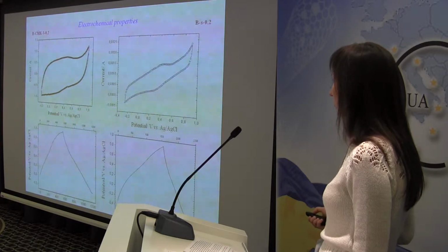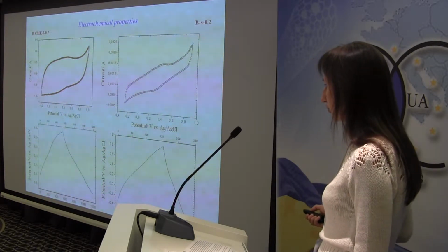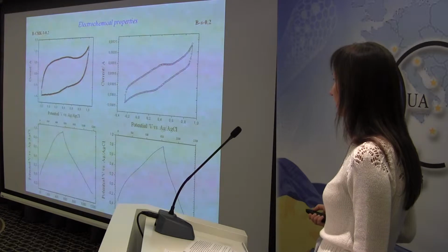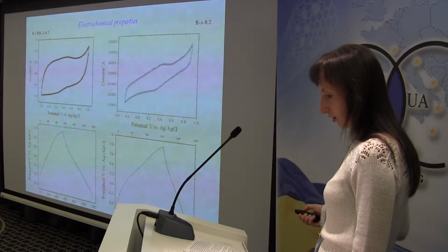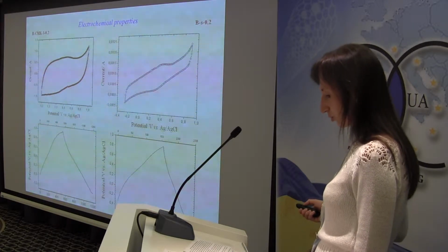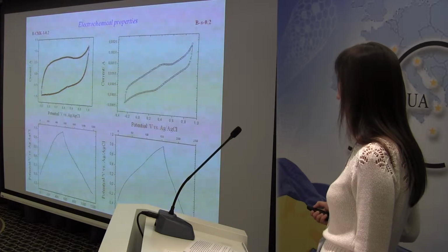It was shown that the capacitance of the obtained carbon materials, especially microporous carbon materials, is up to about 300 farad per gram. The capacity of such materials is due not only to the capacity of the electric double layer, but also to the presence of reactive surface groups, which can enter into redox reactions. The obtained materials are stable during repeated charge-discharge cycles. Conducting 25 cycles does not change the capacity and the form of the cyclic voltammogram.